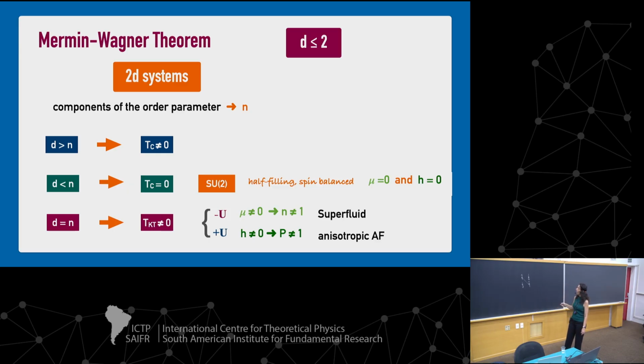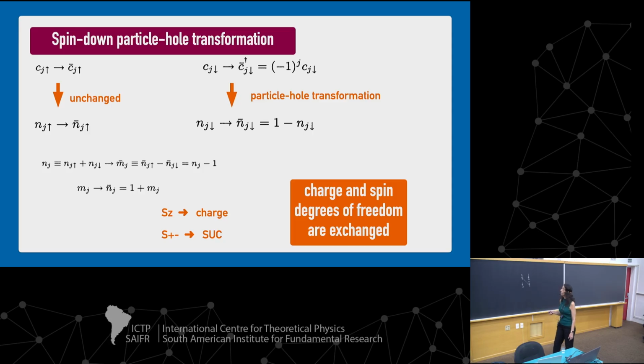This is what we see when we have isotropic antiferromagnetism or half filling in the attractive model. But in the case where the two are equal, so in 2D, 2 components, then you can have this phase transition in the universality class of the Kosterlitz-Thouless, and it happens either when you have attractive U and away from half filling, or repulsive U away from the isotropic case, when you have a polarization. So in these 2 cases, you have the same kind of phase transition, and it allows for critical temperatures different than 0 in 2D.